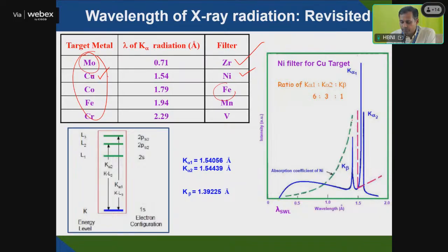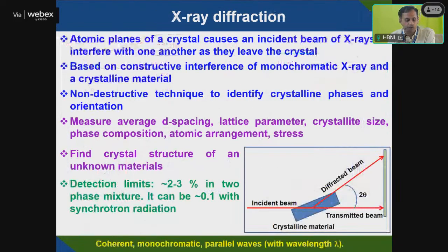You can see here by using a nickel filter, because the absorption maximum of nickel lies in the K beta region, here is the cutoff. So you can easily remove this peak, and you are able to take only K alpha. So coming into X-ray diffraction, all these, the X-ray source and all those things are the main requirement: copper we take as the anodic material, and a tungsten filament was there.